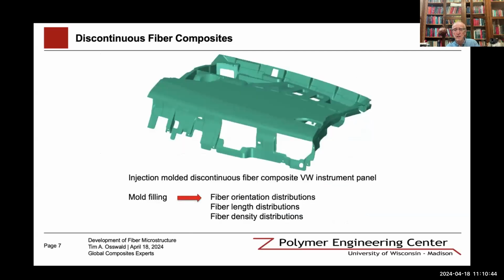So an injection molding of discontinuous fiber composites, this would be a demonstrator part from VW. It's a VW instrument panel. Again, the mold filling is what determines the microstructure within the final part. But as we will see at the end, not just mold filling, but also the injection molding plasticating unit has a big role to play. And I will actually end up with that, which is an area of current research.